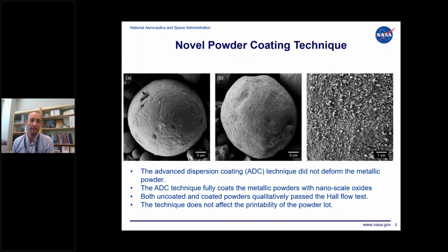Another way to look at it, the image on the left here is of an uncoated nickel, cobalt, chrome metal powder particle, and in the middle you can see what it looks like after we coat it. What was really nice was that this process doesn't heavily deform metal powder. With mechanical alloying, you take very spherical powder, and by the time you're done, it's almost like flakes or plates, and they don't flow very well.